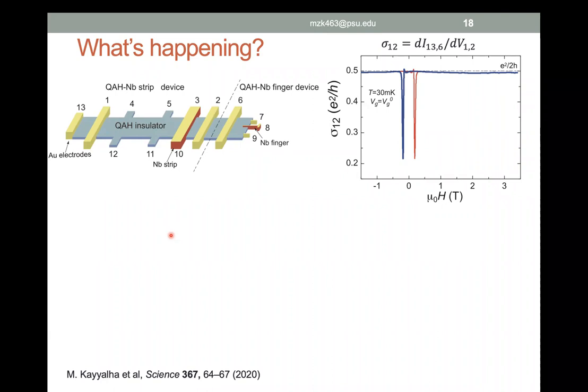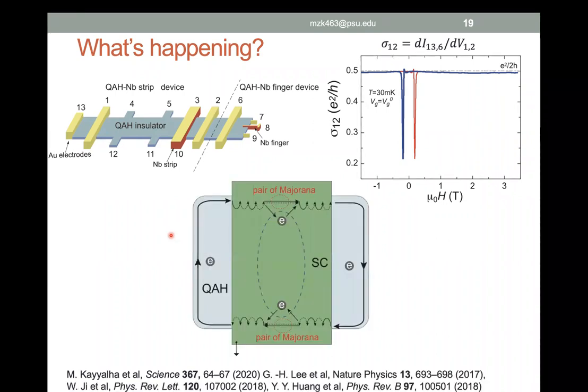And the effect is actually relatively straightforward. It has been observed multiple times in the past in quantum Hall systems. And the idea is schematically shown here. So when you have these millimeter size superconductors, so this green strip here is my superconductor, and then you put it on top of a quantum anomalous Hall insulator, what happens is that the chiral edge mode of the quantum anomalous Hall undergoes Andreev reflection under this superconductor. So depending on the skipping orbit of the quantum anomalous Hall, we believe this is around tens of nanometers. So for a millimeter size sample, it happens, I don't know,